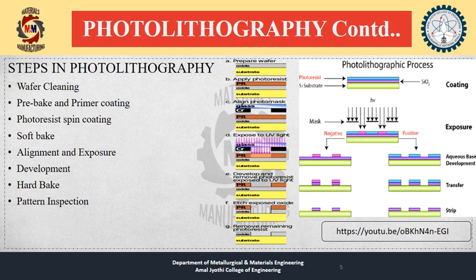The developer chemistry is delivered on a spinner much like photoresist. Developers originally often contained sodium hydroxide. However, sodium is considered an extremely undesirable contaminant in MOSFET fabrication because it degrades the insulating properties of gate oxide. Metal-ion-free developers such as tetramethylammonium hydroxide (TMAH) are now used. The resulting wafer is then hard-baked — typically at 120 to 180 degrees Celsius for 20 to 30 minutes — which solidifies the remaining photoresist to make a more durable protective layer.